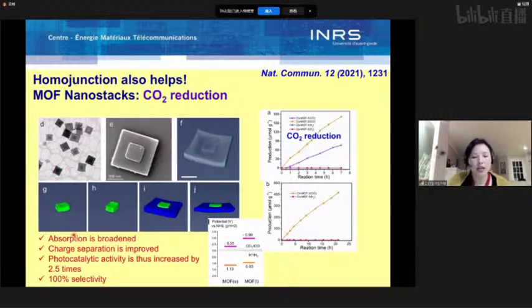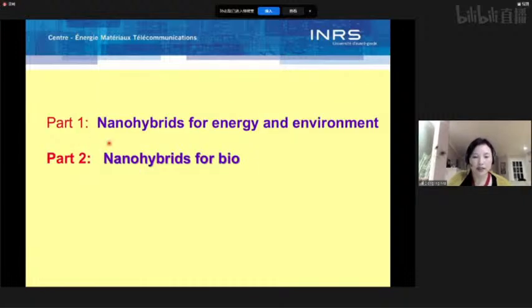Because of that, absorption is broadened, charge separation is enhanced, and photocatalytic activity is increased by about 2.5 times as compared to a single MOF nanoplate. And this hybrid also shows very high selectivity for CO. Basically, no hydrogen was detected, only CO. So we are quite happy with these results. Using this example, I showed that by forming hybrids of MOF homojunctions, photocatalytic activity can be largely enhanced. So with that, I think I can finish the first part.